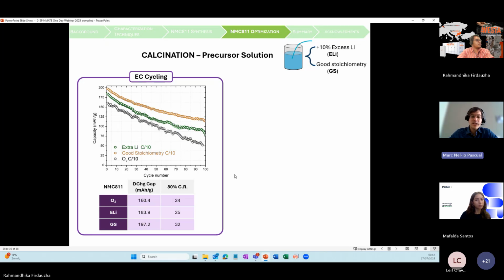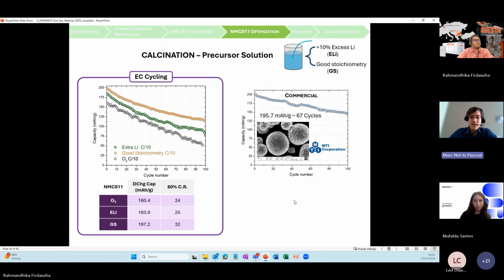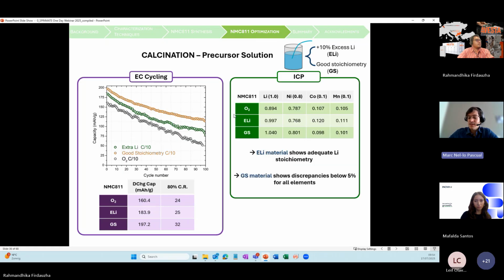And we compare these materials with a commercial sample that we bought from MTI. Can you move to the next slide? That is a sample obtained from co-precipitation. We see that the initial capacity for both of these materials is of the same order. So we have obtained a material with a similar electrochemical performance to the commercial material. So now we wanted to finally check all these physicochemical parameters.